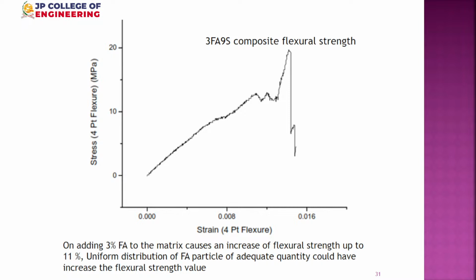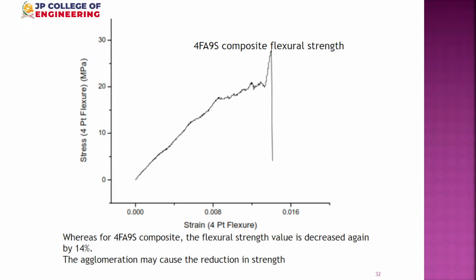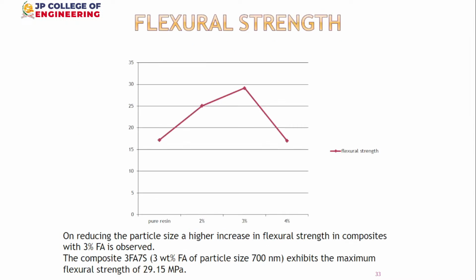Next slide, please. The 700 nanometer shows a very high peak value. There is a relation also there. So this tells about the strength relationship, how the particles participate in load sharing. Next slide, please. So from the flexural strength point of view, the one with 3% and also 700 nanometer gives a very high flexural strength. Beyond which, if you add more, the strength comes down. So this is one of the major conclusions you can write.